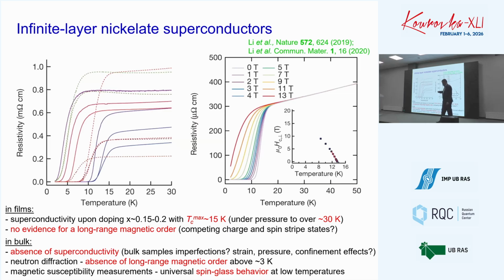beginning they see a clear phase transition to superconductivity, with the resistivity dropping to zero, and upon application of a magnetic field the resistivity rises up, and they see the Meissner effect. This result was immediately, in just 1 or 2 years, well reproduced in very many different systems. Although I think only about 5 or 6 groups in the world are able to synthesize those materials. This is problematic, not easy to synthesize them.